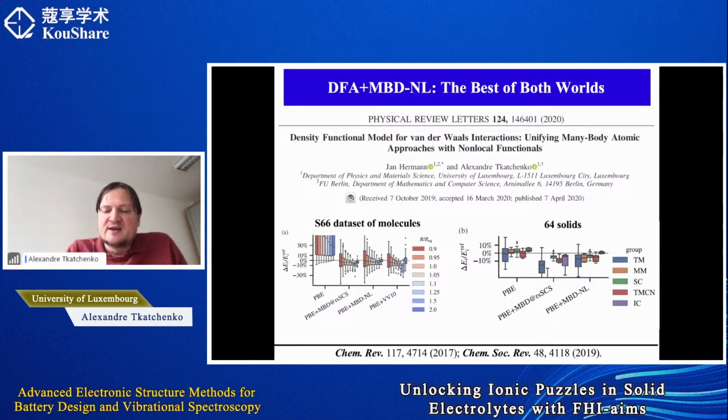And also for solids, the performance is not far from the performance of the parent PBE functional. Now, it's pretty hard to beat PBE. Actually, no one really beats PBE still, I would say, in terms of local, semi-local DFT functionals in terms of its performance for solid state. In contrast, PBE plus MBD-NL works as well as PBE. In contrast, the original MBD functional fails for many of the solids because of so-called overpolarization problems. And so you cannot even carry out MBD calculations for many of the highly polarizing solids.